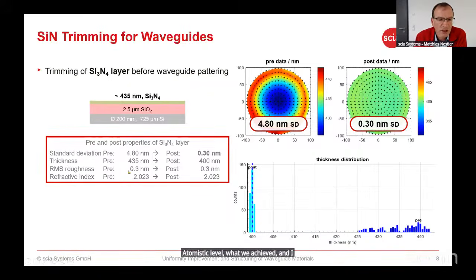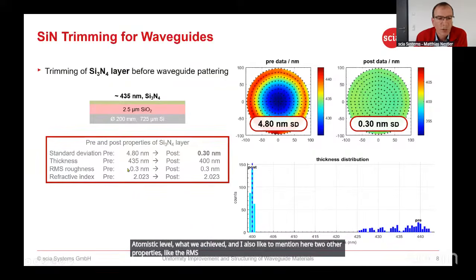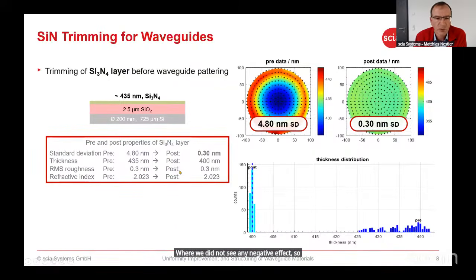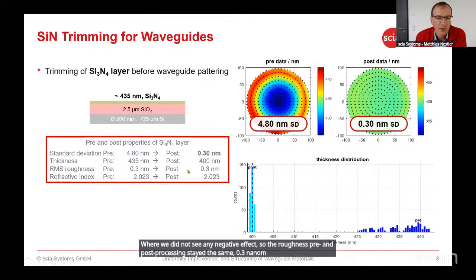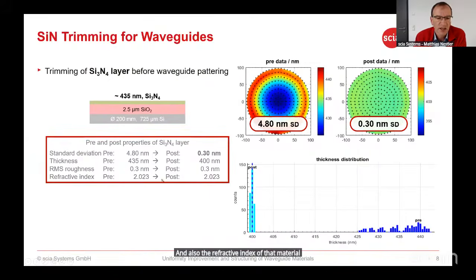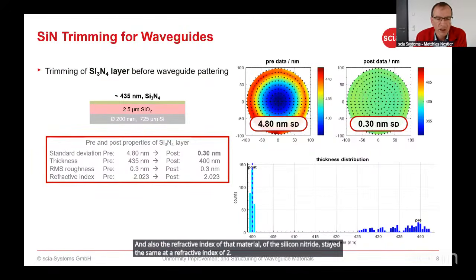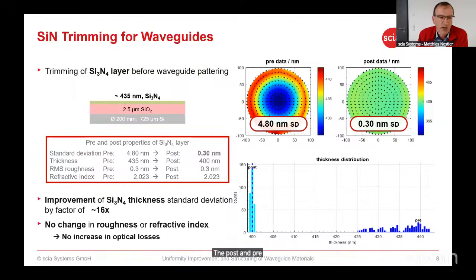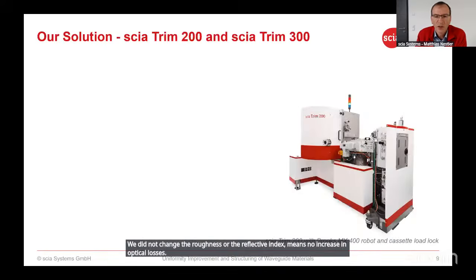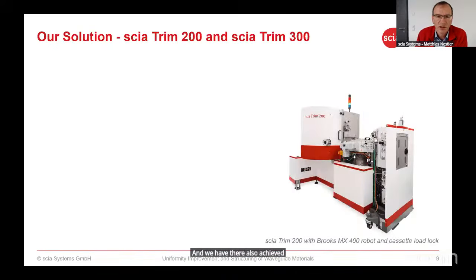And I also like to mention here two other properties like the RMS roughness, where we did not see any negative effect. So the roughness pre and post processing stayed the same, 0.3 nanometer. And also the refractive index of the silicon nitride stayed the same at a refractive index of 2.023. Post and pre is the same. So we achieved the improvement of the silicon nitride thickness standard deviation by a factor of 16. We did not change the roughness or the refractive index, meaning no increase in optical losses. And we have also achieved losses in the range of 0.14 dB per centimeter in some customer applications, but I cannot show any more detail on this.